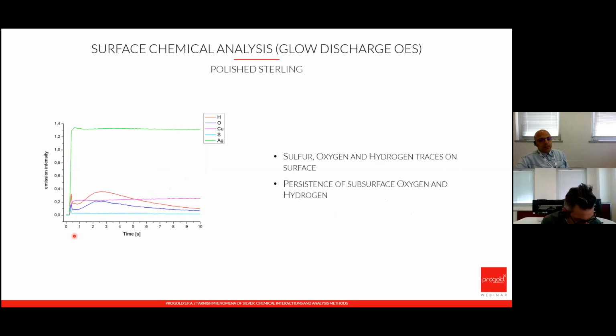Now, before scrolling through the results for each alloy, I shall give you a brief explanation of the analytical response from such a kind of instrument. Each curve with a different color belongs to a specific chemical element. Along the abscissa axis is reported the appearing time of the signal, or rather the depth from which it came, whereas the ordinate axis reports the signal intensity, and it is proportional to the element concentration.